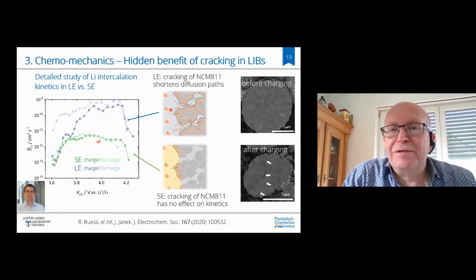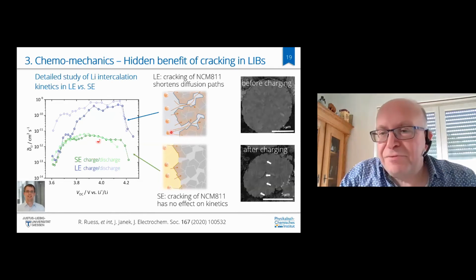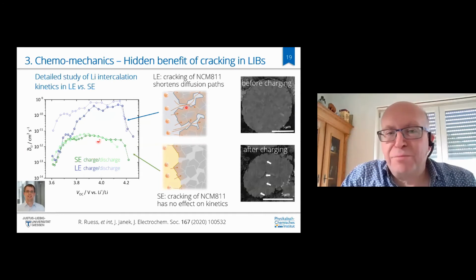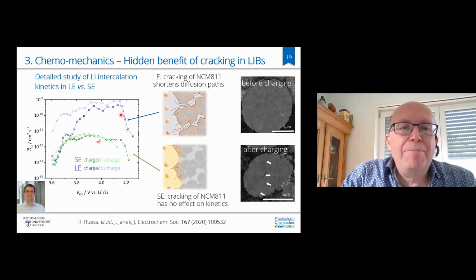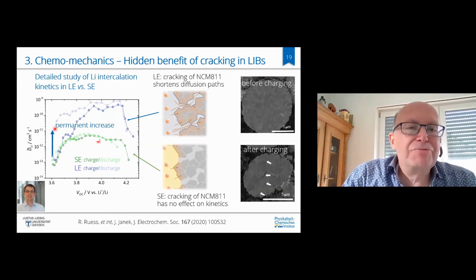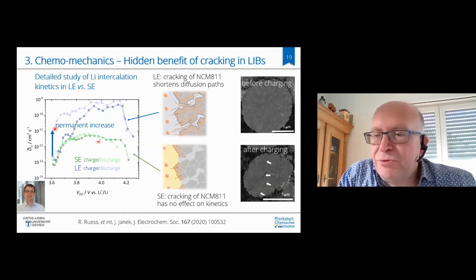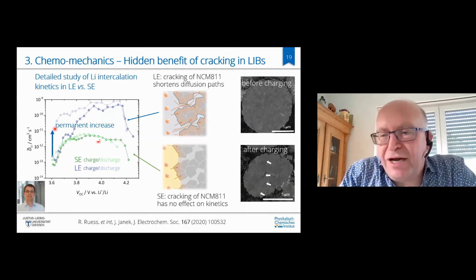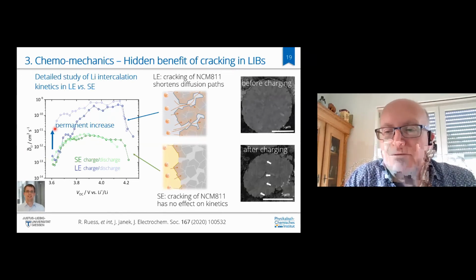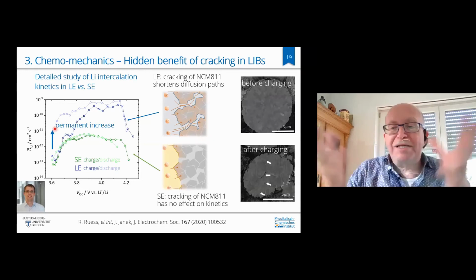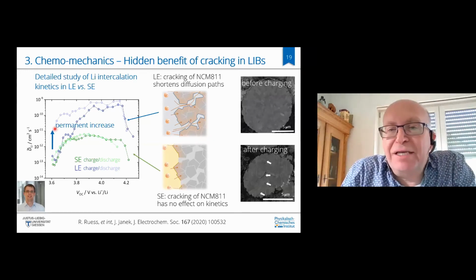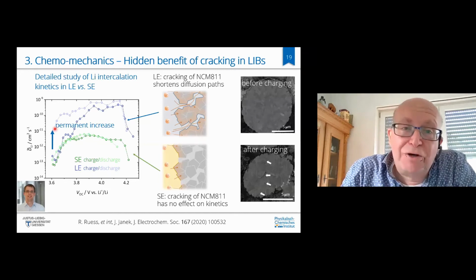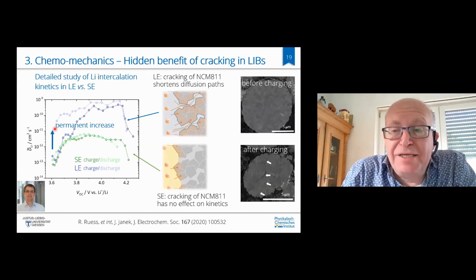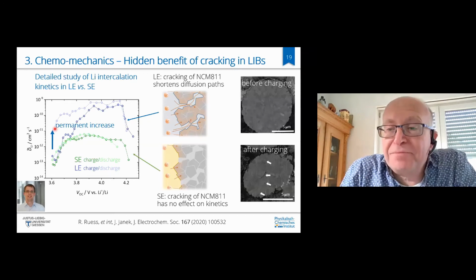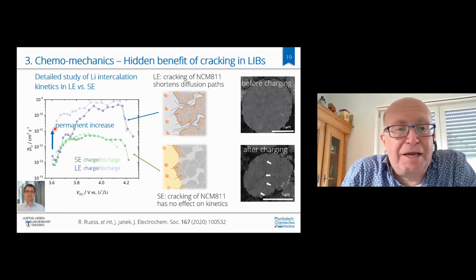Well, our NCM material is cracking, and the liquid electrolyte is invading and impregnating into these newly formed pores. And if we go back, then the chemical diffusion coefficient remains high, almost higher by 2 orders of magnitude. So the cracking of the high nickel materials in this sense in the liquid electrolyte is good because it opens up the particles and allows fast rates. Of course, it opens new surfaces that degrade and lead to faster fading, but in principle, the cracking is good.